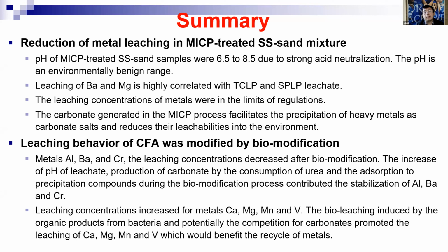And for the fly ash, there are two sides to the biomodification. Leaching concentration is reduced for aluminum, barium, and chromium, because that relates to several things. One is the leachate pH, one is the carbonate generation and adsorption to the precipitating compounds. And for calcium, magnesium, manganese, and vanadium, they seem to increase. So their bioleaching is induced by these organic products from bacteria, and potentially the formation of carbonate compounds may promote leaching of these four types of metals.